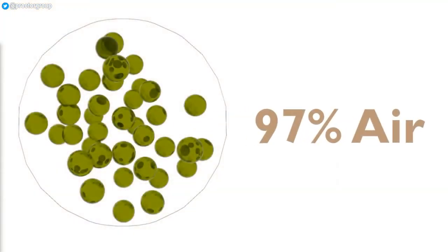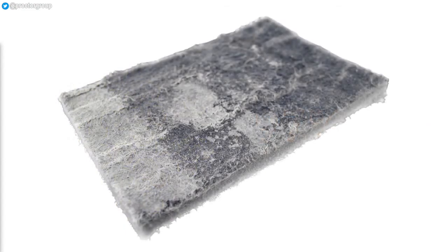The resultant structure is 97% air, entrapped in nano-sized pores, and whilst a superb thermal insulator, it is very brittle, limiting its practical applications. Spacetherm aerogel takes this aerogel and embeds it into a fibrous mat to achieve a combination of excellent thermal performance and robust flexibility.